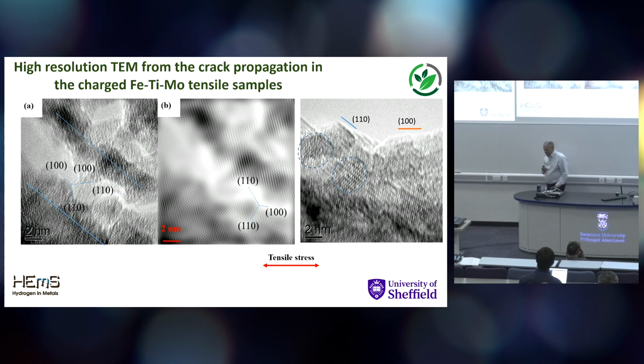I think there are beautiful images here, if you can see them, high resolution. Here on the right, the precipitates are in blue dotted circles. This is the crack path, and you can see it's following, really at the atomic scale, a 110 cleavage, then it switches to a 100, keeps switching as it avoids the strain field as it goes around those precipitates. Really beautiful image there.